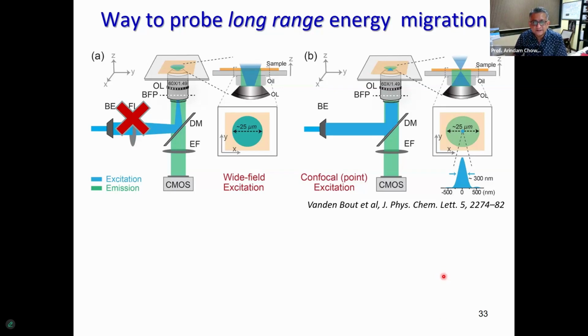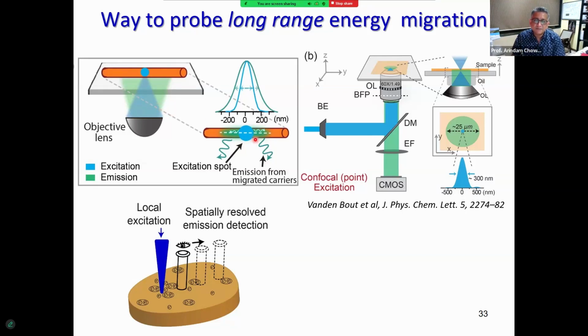He showed that if you take your microscope and remove one single lens, which is the focusing lens, then you can essentially convert an epifluorescence microscope into a confocal kind of excitation. Typically confocal microscopes have a point detector, and epifluorescence microscopes have a CCD camera like your cell phone camera. But if you use a CCD camera, you can locally excite the system. Then if there is carrier migration, you should be able to visualize it because there will be a spread of the emission away from the excitation zone.